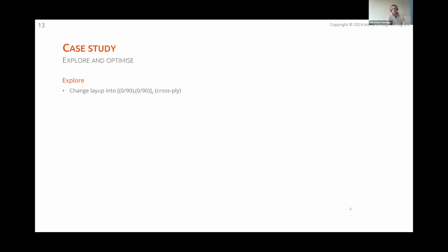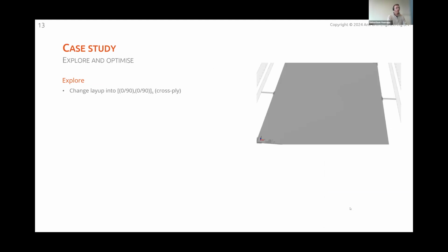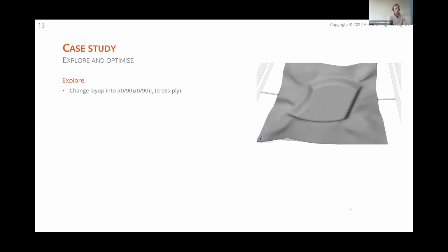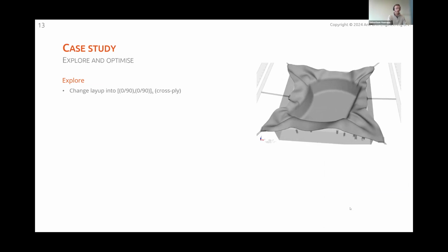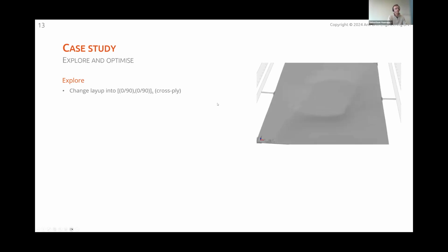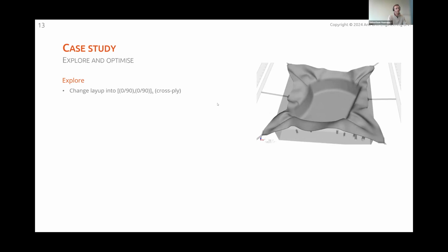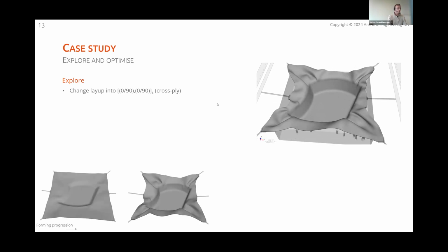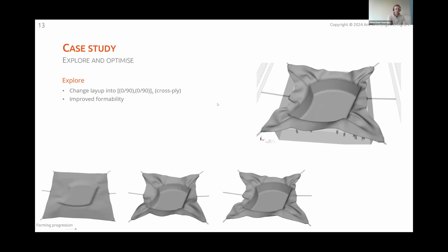Well, we have a simulation to explore things. So we can change the layup, for example, make the laminate a cross ply. So just changing the numbers and do a new prediction. And then the prediction looks like this. Quite different. One more time. So here are the snapshots of the forming of the laminate. And we can conclude when we compare this cross-ply layup with a quasi-isotropic layup that there's quite some improved formability.